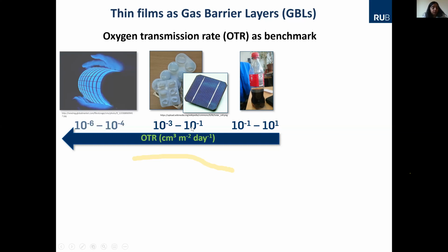But when you go to more exclusive applications, for example, pharmaceutical products, we don't want our medicine to degrade because of moisture. Especially in a country like India, where we have very humid conditions, it's important that we have a very good protective layer. Or even for electronic applications, for example solar cells, you would like a material that has very good barrier properties. So you see the demand is higher, 10 to the minus 3 to 10 to the minus 1. When you go to much more advanced applications, for example in flexible electronics or OLEDs, the range is 10 to the minus 6 to 10 to the minus 4. This is quite demanding, I would say.